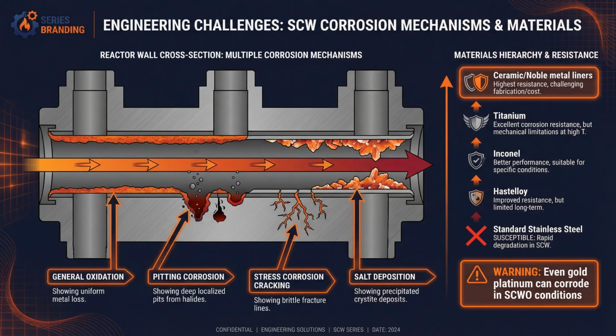Operating under supercritical water conditions presents severe engineering challenges. The combination of high temperature, oxidizing conditions, and dissolved species creates one of the most corrosive environments known to engineering. Multiple corrosion mechanisms attack materials simultaneously: general oxidation, pitting corrosion from halide ions, stress corrosion cracking, and erosion from precipitating salts. Even noble metals like gold and platinum can corrode under these conditions. Materials must be carefully selected, with nickel-based superalloys like Hastelloy and Inconel commonly used, along with titanium for specific applications and ceramic liners for the most aggressive feeds.